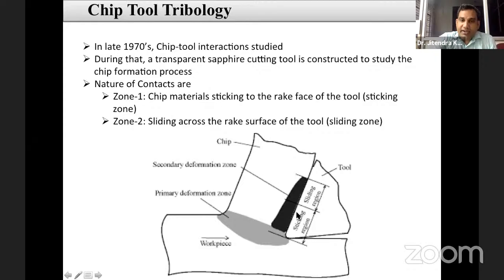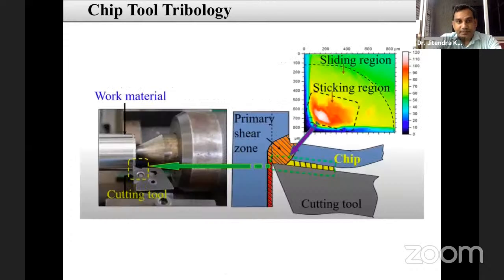It happens away from the tool tip, but the temperature at the tip is very high. So it does not happen right there, but it happens a little bit further, somewhat at the end of the sticking zone and the start of the sliding zone. So this is the reason why the crater wear happens a little bit away from the tool tip.